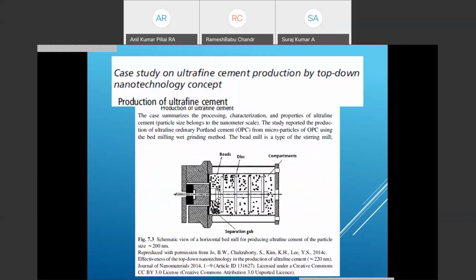Case study on ultra-fine cement production by top-down nanotechnology concept. The case is the processing, characterization, and properties of ultra-fine cement. The study reported the production of ultra-fine ordinary Portland cement from microparticles of ordinary Portland cement using bed milling, wet grinding. It's a type of stirring mill. You can see the beads, the discs are provided on the rod, and there is a separation gap, and there are various compartments.